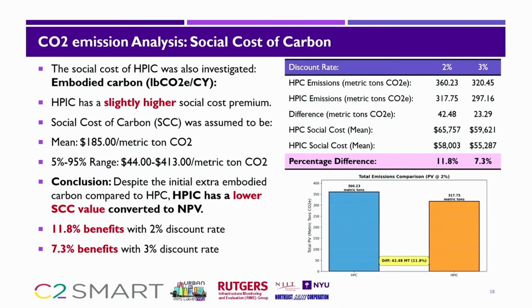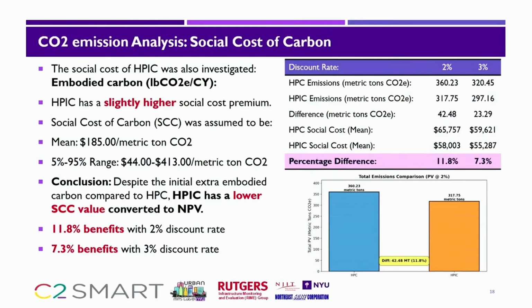And then we tried to do some very simple analysis based on the values in that paper. What we found is that HPIC again has higher benefits, even though it has some higher carbon release in the beginning, over a long time at different discount rates. Again, I don't know if this is going to stay in the final report, but this was a discussion, and these results show that even though the initial carbon footprint of this method is a little bit higher than the regular HPC, in the long run, due to its advantages, it still becomes superior to HPC.